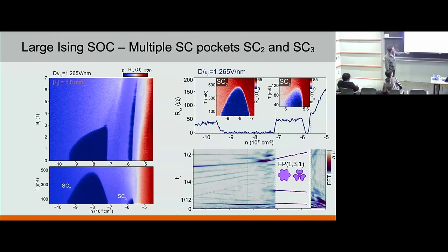So the whole region here is this whole range, but you get superconductivity only in this small section. So the superconducting pocket, this weird phase, 131, is everywhere, but you get superconductivity only close to the boundary of that phase. Essentially, if you go this way, you enter the phase, this 131, you enter the superconducting, then you kill superconductivity with doping, and then you're still there, and when there is another transition, you emerge on the other superconducting phase.